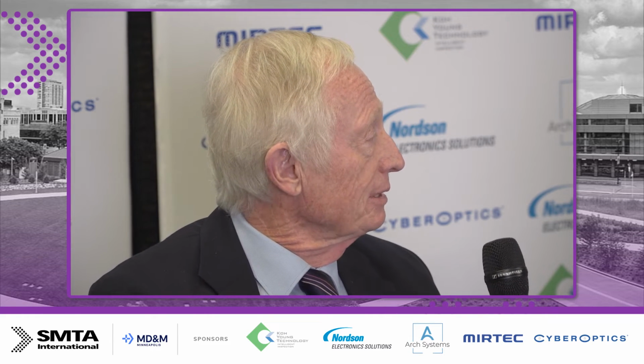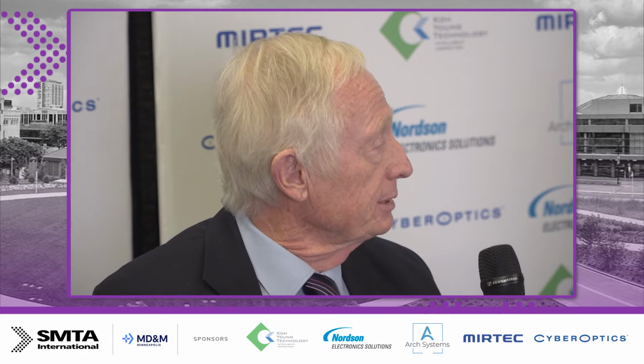Right. So you mean like a buffer in the intermetallic? Well, no. The intermetallic's not the issue here. It's like airbags, something like that. You know that if bismuth gets a high impact loading, it's going to crack. If you can build a little wall around it, and what the silver does is strengthen that wall, and the antimony strengthens that wall through solid solution hardening and things like that, or precipitation hardening, then you've got a little barrier there that will protect the bismuth from the stress that would otherwise crack it.